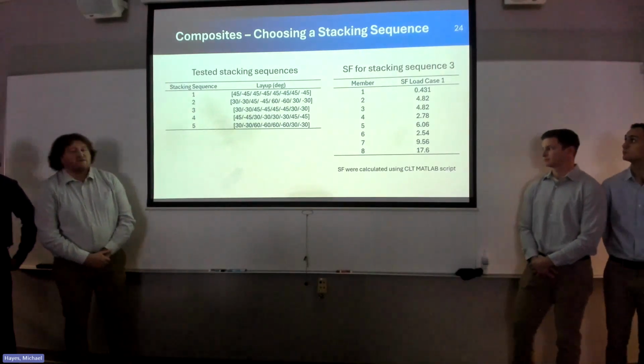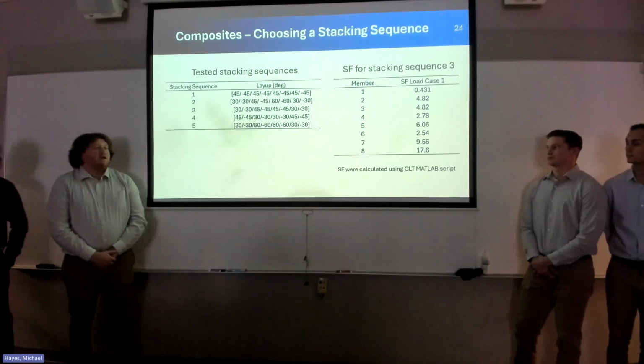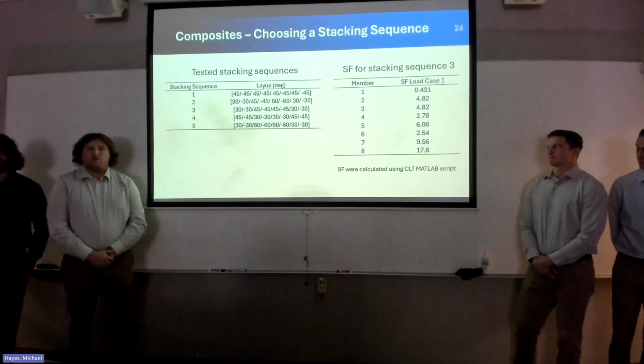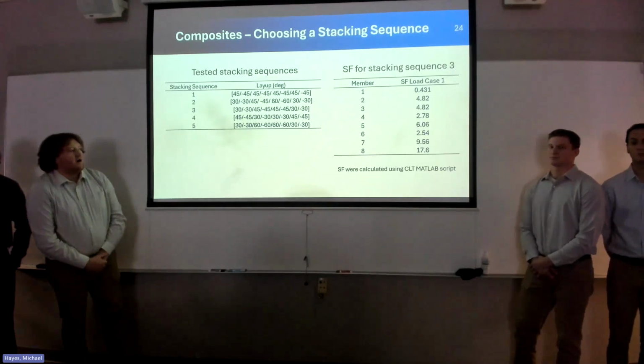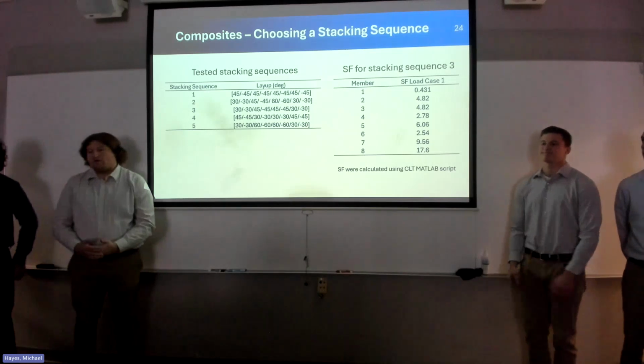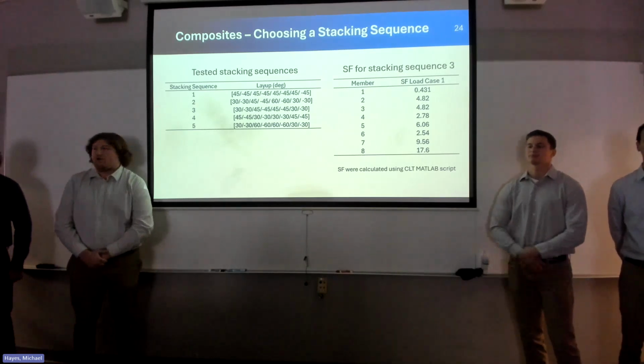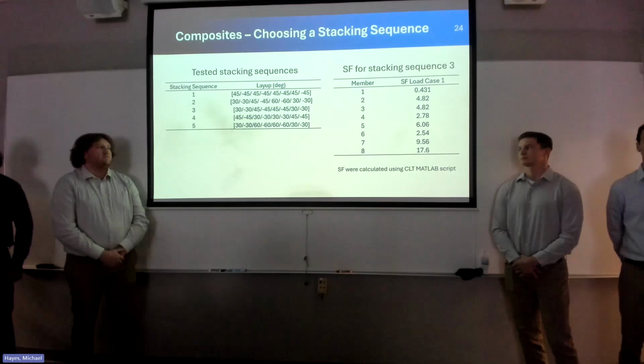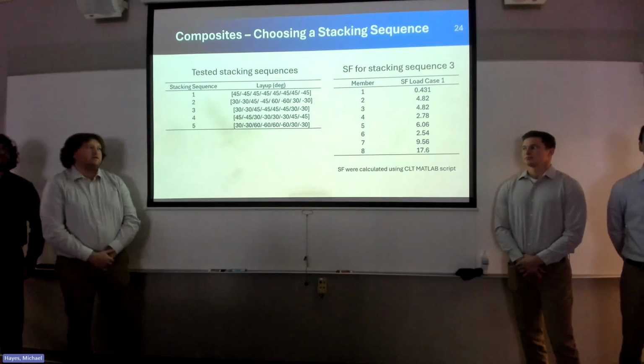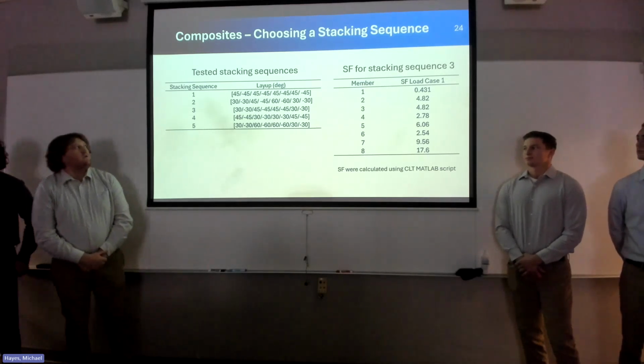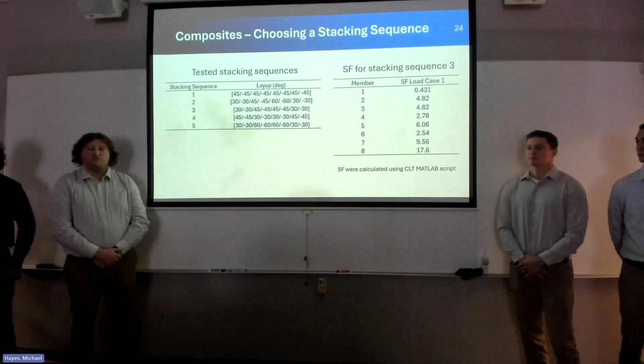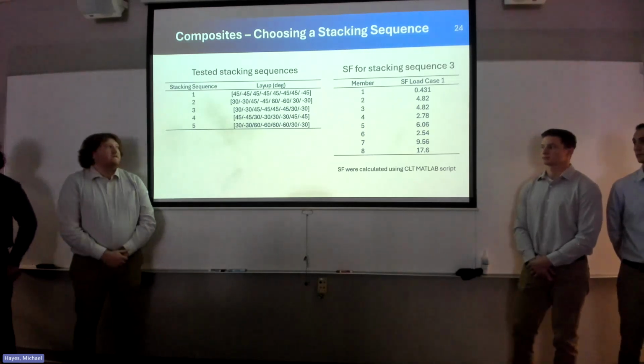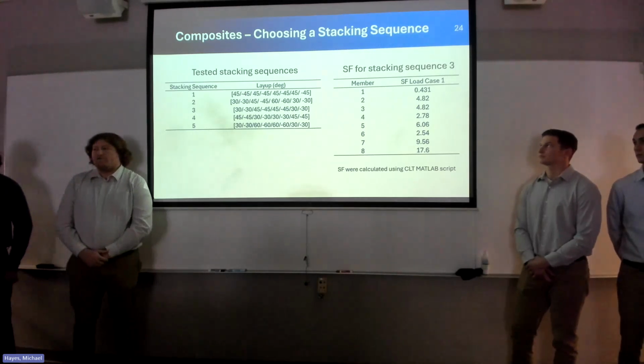As far as testing stacking sequences, I tested 5 of them, and they do all incorporate those limitations I talked about for filament winding. And then as far as failure criterion go for composites, there's a couple of them. I did choose the most conservative one when calculating the safety factor. After calculating all of them, stacking sequence 3 produced the highest safety factor for a majority of the members.